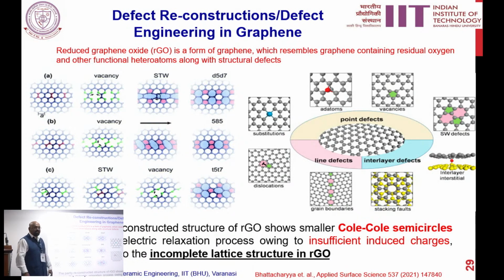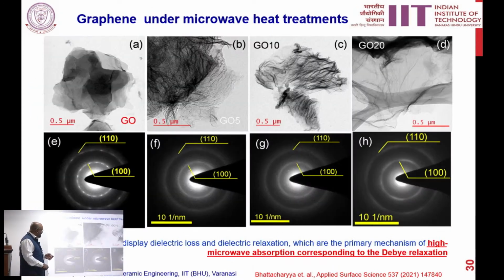So what are the defects? Adatoms and different kinds of surface reconstruction. Specifically, there are line defects, interlayer defects, grain boundaries, stacking faults, dislocations, and a lot more. Each of these defects has a role in graphene. They basically produce a localized electron concentration. That localized electron concentration absorbs light, meaning electromagnetic radiation. So the radar, which sends electromagnetic radiation, is absorbed by that specific device. This has some insufficient charge, and along with graphene it produces a magnetodielectric surface.